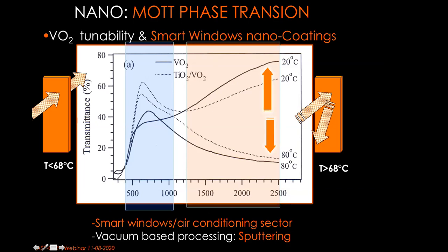You can see, colleagues, that if a thin film of VO2 is coated on a glass, if its temperature is at around 20 degrees Celsius, the transmission of this thin film is quite high. It can go nearly 80% to higher infrared, so it's around 75%. It's highly transmitted. So the infrared radiations are highly transmitted in this region when the temperature of this film of VO2 is 20 degrees Celsius. When you heat that film at about 80, or above 68, its transmission is given by this black curve here, and the transmission is less than 10%.